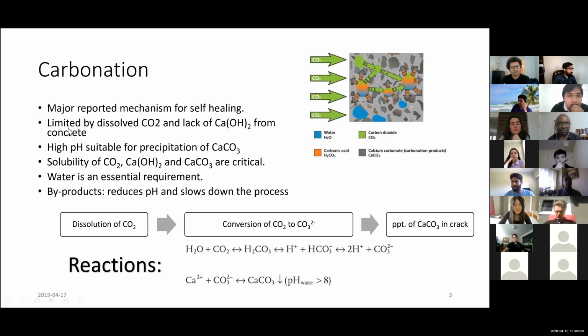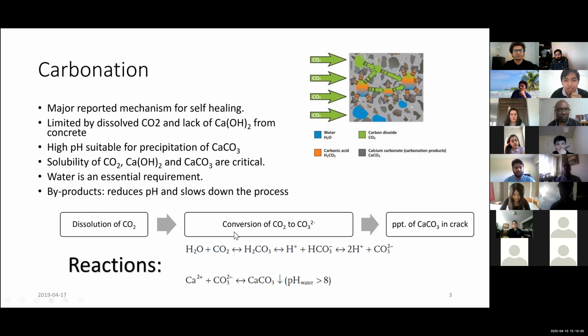In carbonation, it has been reported as the major autogenous healing mechanism, and it is currently limited by the carbonation which happens atmospherically by itself. It's limited by the amount of dissolved CO2 from the air outside, and also a lack of lime, like calcium hydroxide in concrete. High pH is suitable for the precipitation of calcium carbonate, but a system of carbonation is not able to maintain a high pH because of the following mechanism.